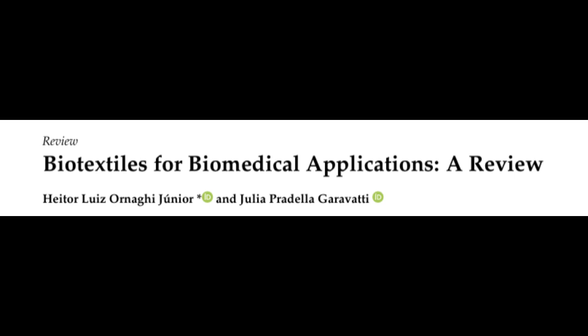Even for eyes. Delivering drugs to the eye seems tricky. It is, but they're exploring cross-linked hyaluronan electrospun nanofibers. These were loaded with ferulic acid, an antioxidant, and interestingly, they also added an antimicrobial peptide, so dual action. Did they work? The dimensions, the drug loading, the release profiles, they all looked promising for ocular applications. And acne. Something more common. Tretinoin-loaded nanofibers for topical treatment. The idea is sustained release, better stability under refrigeration, maybe even on-demand delivery. Could be more effective and convenient.